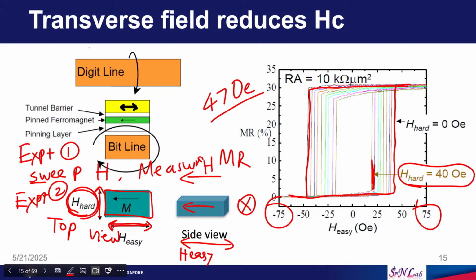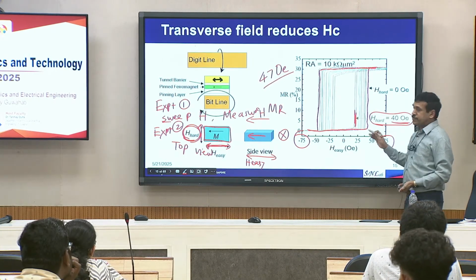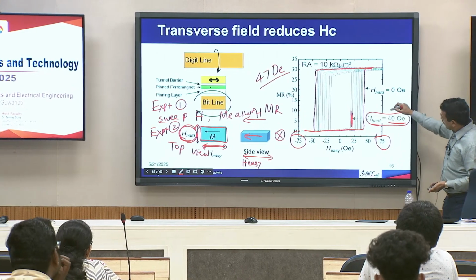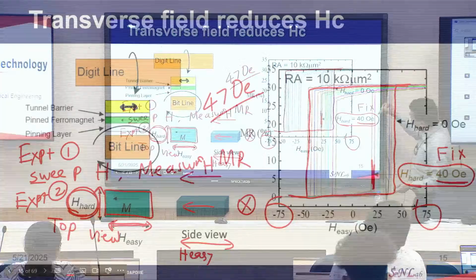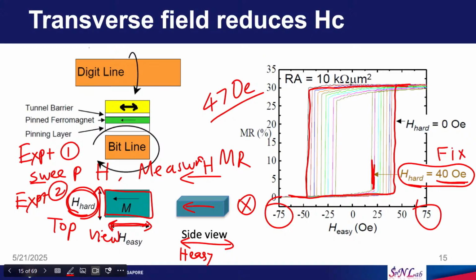Let us take this curve, 40 Oersted. We apply a magnetic field in the hard direction and its magnitude is 40 Oersted. We are not sweeping this; it is a fixed value of H hard. We are only sweeping the field in the easy direction, like what we normally do for measuring a hysteresis loop. In this case, when I measure the hysteresis loop, it looks something like this.